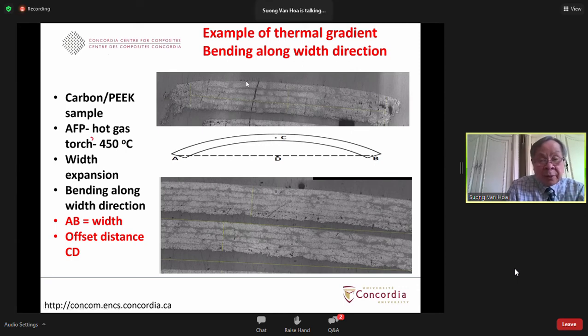So this is a schematic representation of the width of the laminate. You take the midpoint A on the left and the midpoint B on the right, and you connect them with a line. If there is no bending, then the points C and D should be the same. But if there is a gap here, there is bending. The picture below shows one laminate. You can see that the line BC is here, AB is here, that's the yellow line here. And also along the line CD, there's a gap. The same thing for the laminate below. You have the line AB here, and the line CD here, and it shows that you have a gap. The reason for this bending is the thermal gradient that is developed.